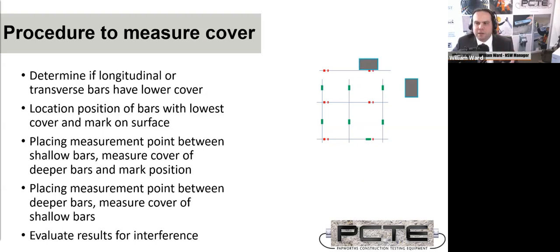After that, we can then go back and pick an appropriate measurement point for our critical cover measurement, which is the bars closest to the surface with the lowest cover, and we can record our cover depth of those. If we don't know where our bars are, it's very easy to pick a point across where you've got the crossing bars. So this procedure should always be your backup. The other thing is, by locating the bars, you'll also know the distance between them as part of your procedures. So you'll know to use your neighboring bar correction or your other techniques for correction after the survey.